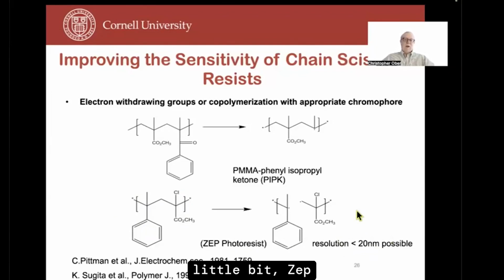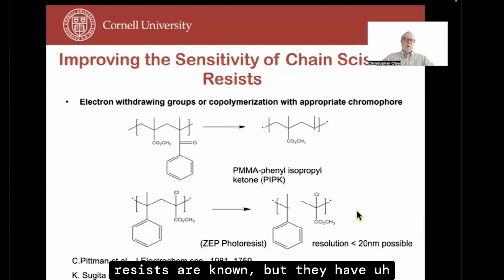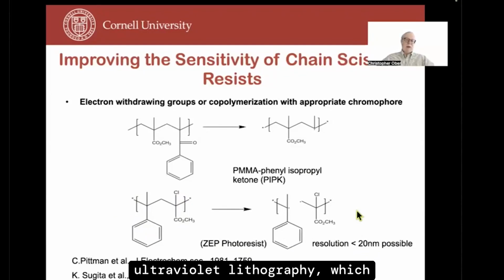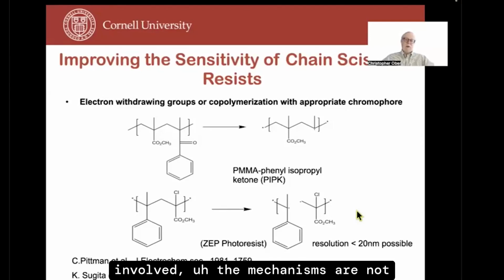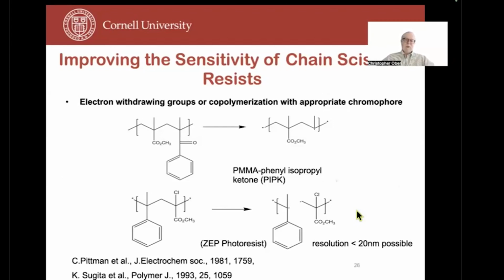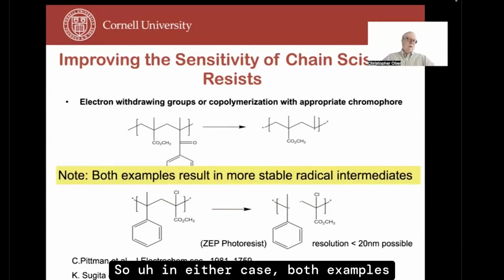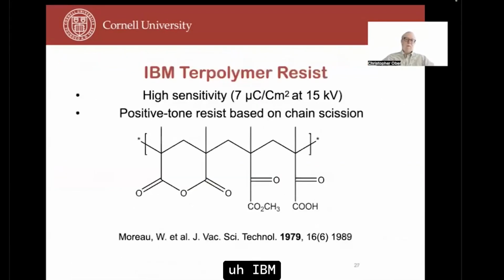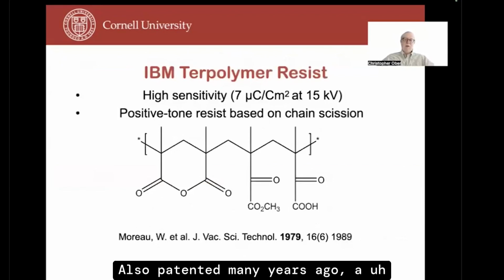Interestingly, jumping ahead a little bit, ZEP resists are known, but they have not been explored for extreme ultraviolet lithography, which suggests to me that although electrons are involved in e-beam and chain breakage is involved, electrons are involved in UV lithography and chain breakage is involved. The mechanisms are not the same. And so it's tempting to say, just use an e-beam resist at extreme ultraviolet wavelengths. That's not proven to be the case. There are important and subtle differences. Okay, so in either case, both examples result in a more stable radical intermediate, and that leads then to better performance.